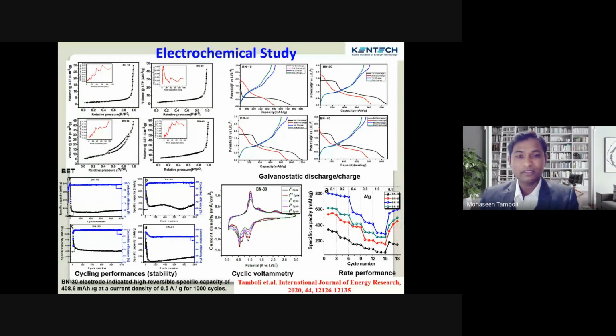After that, we studied galvanostatic charge-discharge in the lithium-ion battery, and you can see the BN30 sample showing a high specific capacity compared to all the other electrodes. We also checked the cycling performance stability, and you can see the BN30 sample showing high stability and efficiency compared to other electrode materials. After that, we checked the materials at different current densities. At different current densities also, the BN30 sample shows a high specific capacity compared to the other BN electrodes, at current densities like 0.1, 0.2, 0.4, 0.6, 0.8. At every current density, the BN30 electrode shows a high specific capacity.